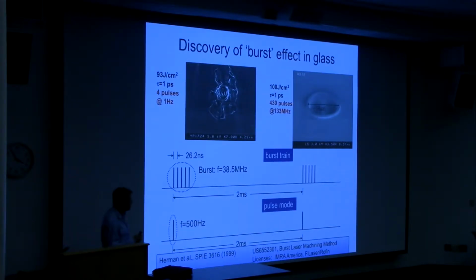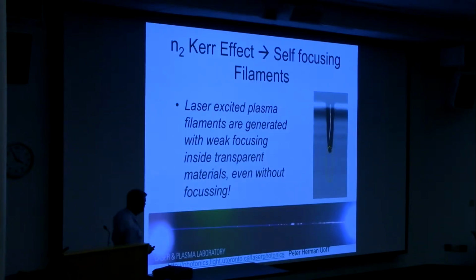And so this heat accumulation effect under so-called burst modes became a patent application. It actually led to a license. We didn't do it very well, didn't get rich or anything, but now, in fact, 20 plus years later, it is an important industrial process today because the lasers are reliable and it has this enhanced machining effect that's really a lot of fun. So there is this parameter of repetition rate that's very important.